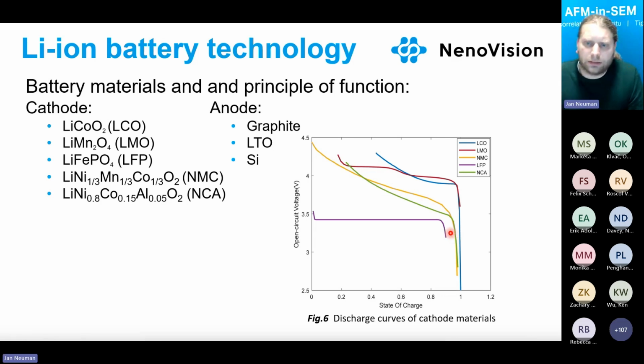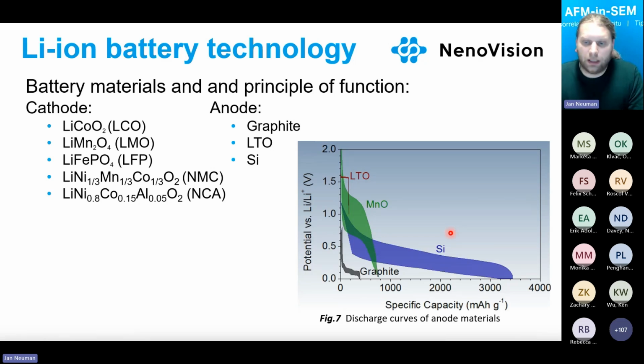So we have to understand the behavior of each material to be sure that we work with the battery in a proper way, and we cycle it, for example, in the right potential windows. In the case of anodes, the situation is the same. Currently, the most common material is graphite. Graphite has quite a low discharge and charge voltage against lithium.